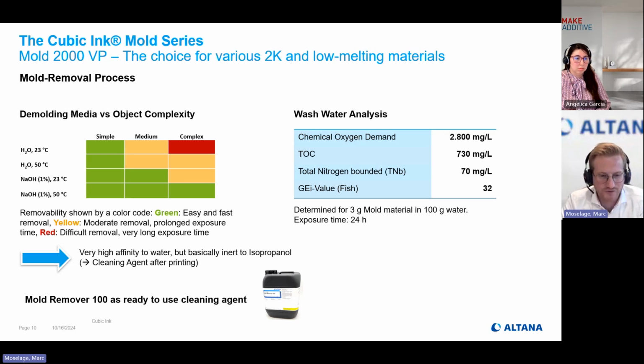It is of course this thing, okay, the material is very hydrophilic, it attracts water, but it is basically inert to many nonpolar solvents such as isopropanol. And this is important because you also need to clean the material, right? When it comes from the printer, the material needs to be cleaned, but you've got to make sure that the cleaning fluid you clean your part, the mold, with after printing doesn't dissolve the whole mold. It is important to know. So isopropanol works very well for cleaning, very bad for dissolving, which is a good orthogonal behavior.